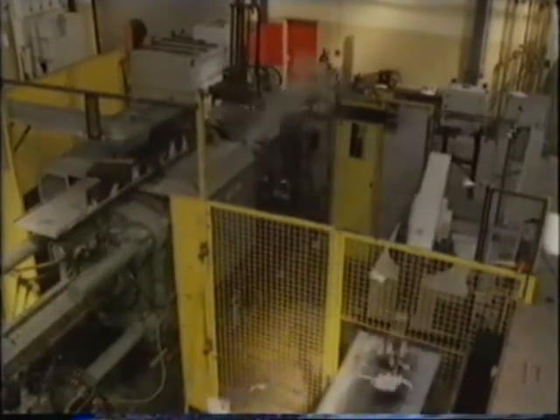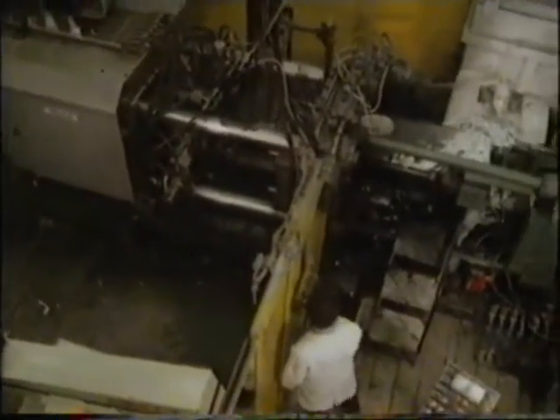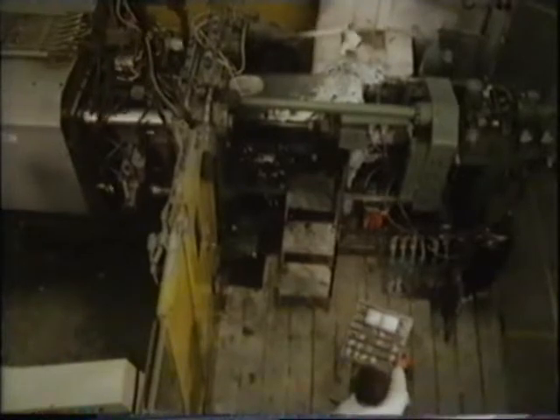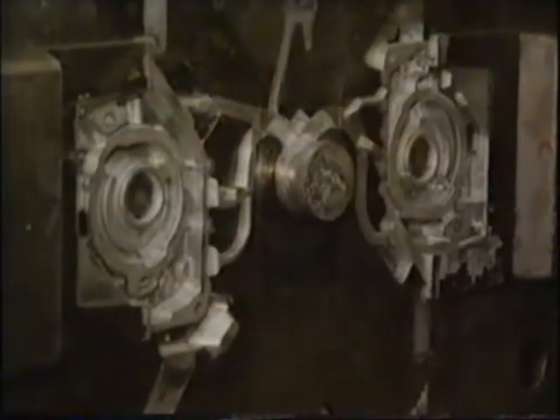Between each injection of the metal, the die is sprayed with a graphite-based oil to help prevent the metal sticking to it. Because of the high pressures involved, safety regulations mean that the machine is heavily guarded. The metal injection plunger on the machine moves in 4 phases. The closing of the pouring hole, moving the metal up to the gate in the die, a very rapid movement to fill the cavity as quickly as possible, and last, an intensification to compact the metal and reduce cavitation. That way you should end up with a perfect casting every time.